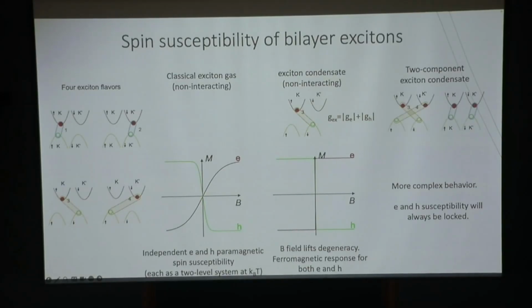Things could also be a little bit more complicated if you introduce interactions between the excitons. If you have exchange interaction, it's actually possible to stabilize a two-component exciton condensate, where it's forced to have, let's say, both intervalley excitons or both intravalley excitons. In this case, the spin susceptibility will be a little bit complicated. But nevertheless, one thing we expect is that electron and hole will have strongly correlated behavior, with the same spin densities.